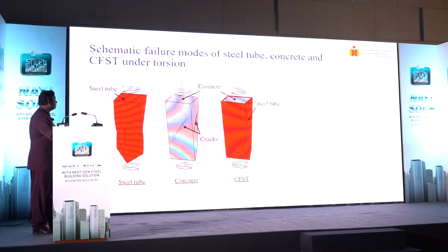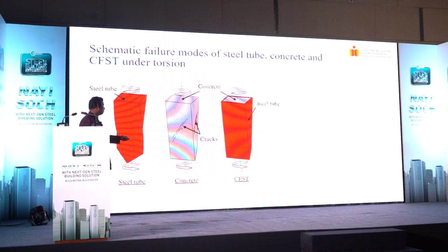And then we subject it to torsion. Again, the first one, the second one, are not going to resist very well, also having cracks. But when you put concrete inside a steel tube and you try to twist it, you have much higher resistance against torsion for an infill concrete.